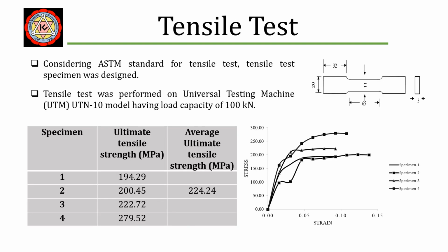In the same manner, tensile testing was performed by considering the ASTM standard. The tensile tests were performed on a universal testing machine having the model number UTN-10 with a load capacity of 100 kilonewton. As already mentioned, due to the limitations of the materials to perform all the tests, sand castings had been done to perform the test. So all the tensile testing specimens were from the sand casting. The ultimate tensile strength was found to be 224.24 megapascals.